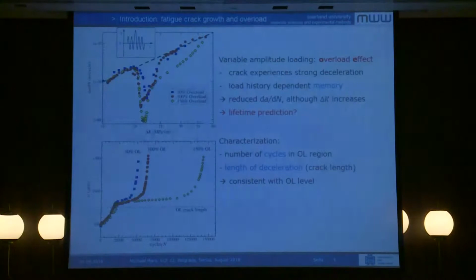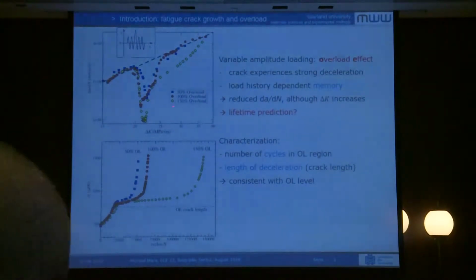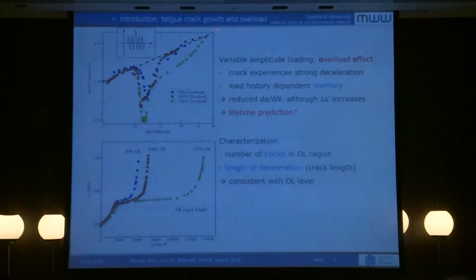And what happens then? You would expect that if you have such an overload, this is not good for the fatigue behavior, but it is the opposite way. If you have a look here on the dA over dN diagram, you see that you have retardation in the crack propagation rate up to 1/10 of the crack propagation rate, and this lasts for several, maybe 1,000 cycles up to this point where you have the crack propagation rate you had before, and this increases your lifetime, as you can see here.